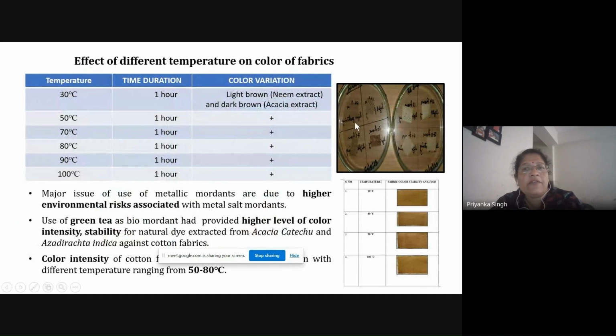Then we have studied the effect of different temperatures on these dyed cotton fabrics, after one hour of incubation at different temperatures varying from 50 to 100 degrees Celsius. For the Azadirachta case, we have seen a very similar color intensity up to 100 degrees Celsius. A similar finding we have seen for the acacia at 100 degrees Celsius. This shows that green tea as a biomordant associated with this dye extract has shown very good stability and color intensity. So green tea can be used as the best biomordant system for developing our natural dye.